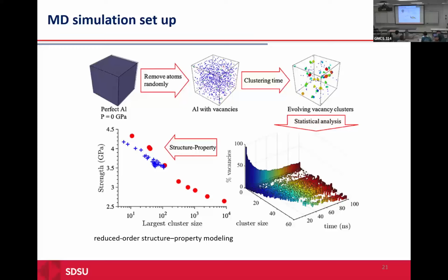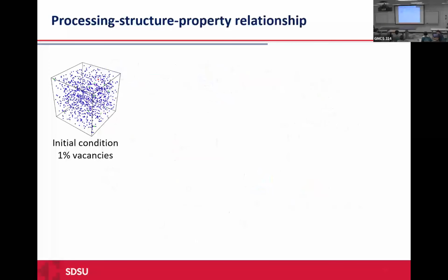Then after some time, if we look at this microstructure, if we give it enough time, we can see that those vacancies are clustering together and make larger clusters. And we can look at the distribution of this cluster over time and how their size is changing over time, and what is the percentage of those vacancies at each size as well. Then we can just apply some loading on the sample at different time steps to see how the larger cluster size would affect the strain of the material, or how this microstructure that is happening after shock loading is affecting the material properties.